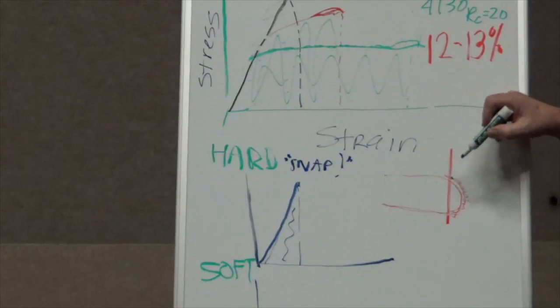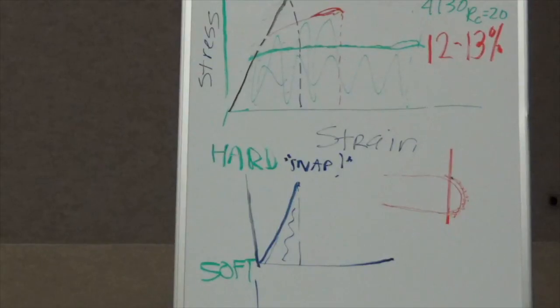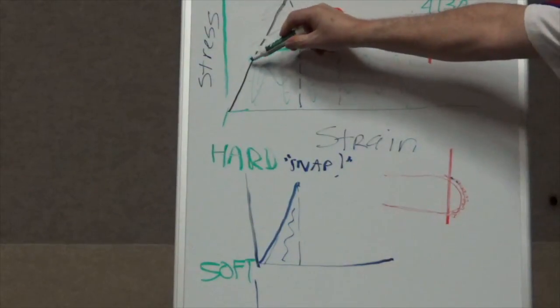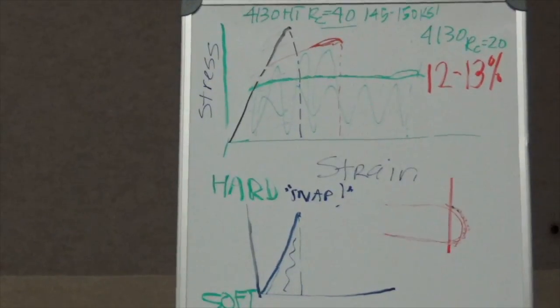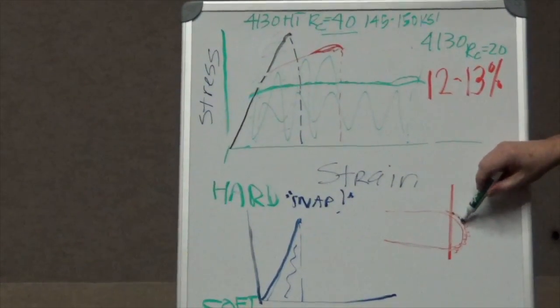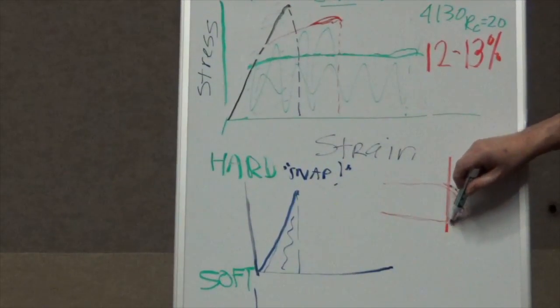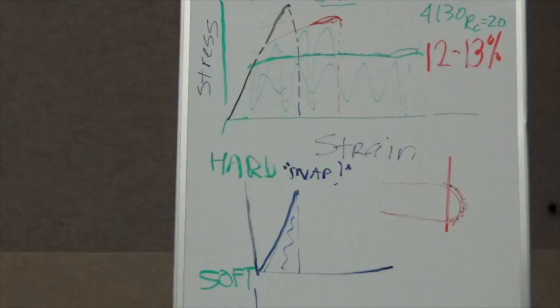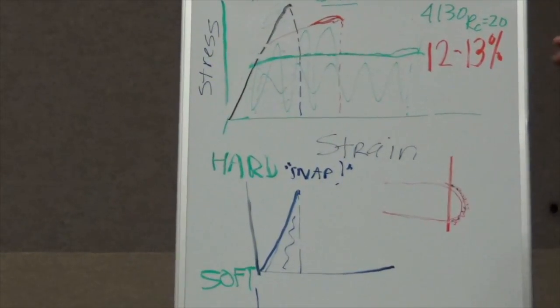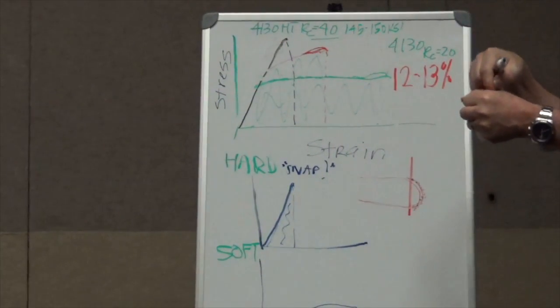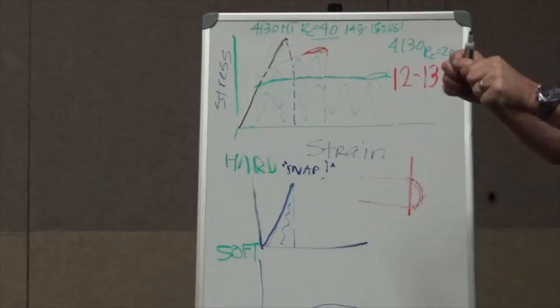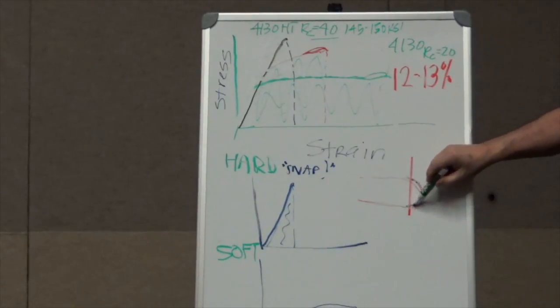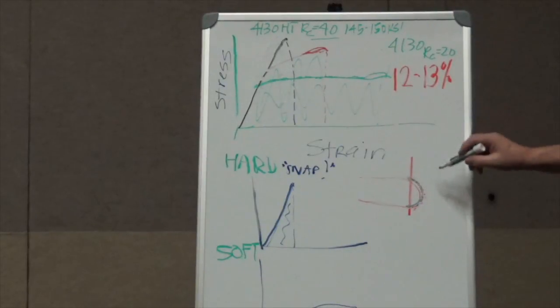And what will happen is that it will hold on, hold on, hold on, and then at some point it will release. And if the material has ductility, it will cold work. It'll slightly release and then it'll go to another spot. It'll do that same thing where the stress strain at a micro level is real, real high. It will actually crystallinely move, and it will give that strength up. If the material has ductility, it will literally do this thousands of times before it fails. So it'll micro-deform, spread the stress out, go to the next highest area where, again, that pinpoint stress is really, really high. It'll micro-deform, move on to the next one. So this is the mechanism of failure in tubes, without a doubt.